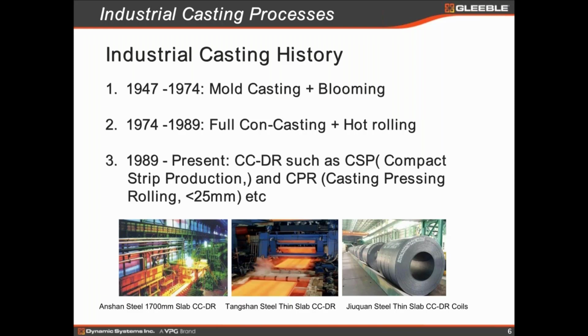It's really focusing on the mold casting and the blooming, which means you have to break the ingot to start the rolling after that. And then from 74 to like 89, in about 10 to 15 years, continuous casting really started. But at that time, they were not integrated. You still needed to separate the casting; rolling is rolling, right? So that's why I didn't say direct rolling, I still said hot rolling.